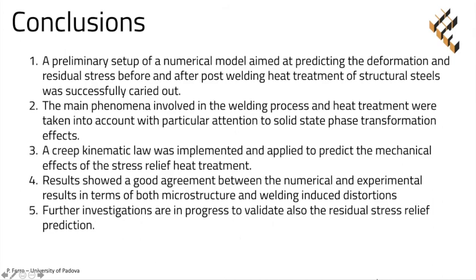So we arrived at the conclusions. Number 1, a setup of a numerical model aimed at predicting the deformation and residual stress before and after post-welding heat treatment of structural steels was successfully carried out. Number 2, the main phenomena involved in the welding process and heat treatment were taken into account with particular attention to solid-state phase transformation effects.